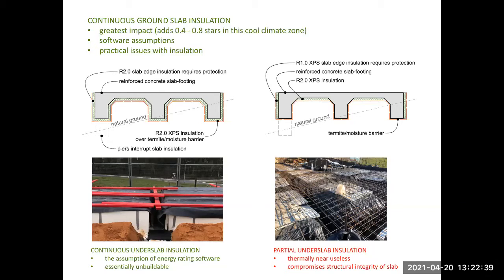But the big issue here is that all rating software assumes that under slab insulation is continuous. Raft type slabs have got stiffening and reinforcing beams that are not normally insulated. And so under slab insulation is typically only installed to the flat underside areas of the slab. In practice, this means that as much as 30% or more of the slab is not insulated.